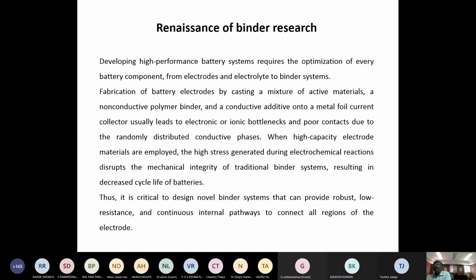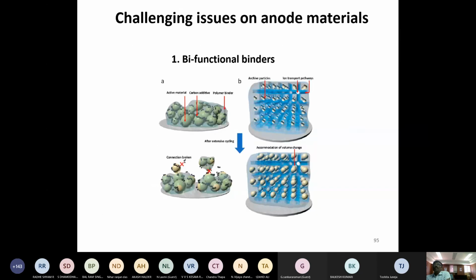But unfortunately, when you use SiOx, the binder is another problem because the conventional binder which is used to bind the electrode materials, we are using PVDF, polyvinylidene fluoride, but that cannot be used as binder for silicon monoxide because the van der Waals force is insufficient to hold the particles. So you can work on polyacrylic acid or CMC, carboxymethyl cellulose, or a blend of these two components. So these are the challenging issues on the anode side. So you have to find a suitable binder to hold the particles.